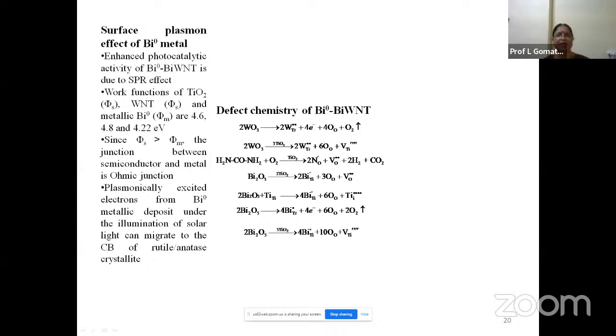That is, tungsten, if it takes a titanium lattice site, there are 2 excess positive charges. For compensation of these excess charges, 4 electrons are present, and a vacancy in titanium is created. So W6+ ions ×2 means 12+, Ti4+ ions ×3 means 12+. So for every 3 titanium ions, 2 tungsten ions can replace them. That's how titanium vacancies are created.